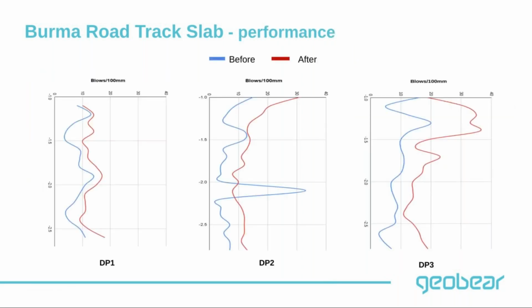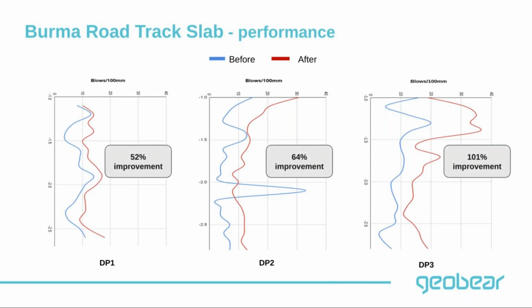And then we carried out some dynamic probing measurements before and after the treatment, and these are the different samples we had. The blue lines represent the dynamic probing results before the treatment, and the red lines represent the results after the treatment. You can see that, generally, we had an improvement of between 50% and 100% in the values of dynamic probing. So that would reflect in higher stiffness values of the substructure.